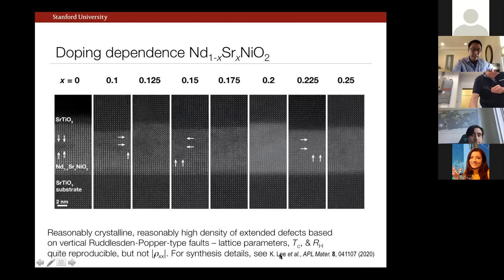But let me simply say that the structures we're finding are likely to be of the variant of having anti-phase boundaries, as well as, in particular, Ruddlesden-Popper-like layered intergrowths. Okay. What this means then is for bulk volume sensitive measurements, like TC or the lattice constants, or the static Hall field, as I'll show you,